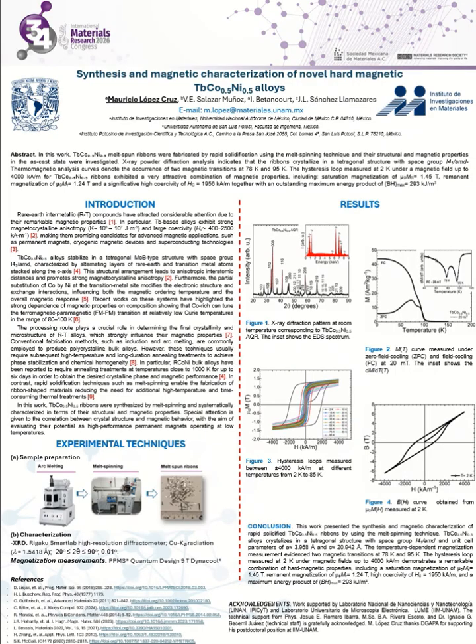In conclusion, this work presented the synthesis and magnetic characterization of rapidly solidified terbium cobalt nickel ribbons. These alloys crystallize in the tetragonal structure. The temperature-dependent magnetization measurement evidenced two magnetic transitions at 78 and 95 Kelvin. The hysteresis loop measured at 2 Kelvin demonstrates a remarkable combination of hard magnetic properties, including a saturation magnetization of 1.45 teslas, remanent magnetization of 1.24 teslas, high coercivity of almost 2000 kA/meter, and a maximum energy product of almost 300 kilojoules/meter cubed.